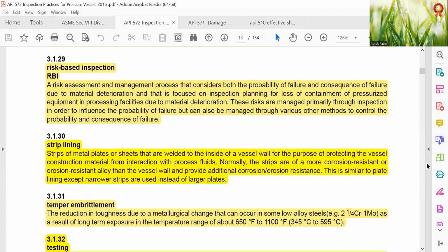Temper embrittlement: the reduction of toughness due to metallurgical changes that can occur in some low alloy steels, such as 2.25 chrome 1 moly, as a result of long-term exposure in the temperature range of about 650 degrees Fahrenheit to 1100 degrees Fahrenheit, that is 345 to 595 degrees centigrade.